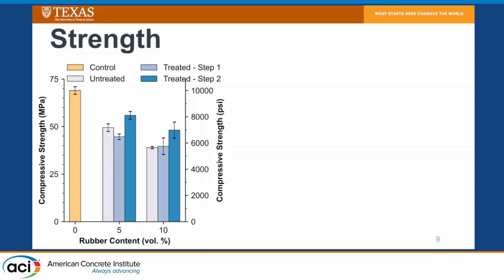As I stated before, once we start introducing rubber into our composites, we get this reduction in strength, so that wasn't surprising. We do see that when we compare the untreated bars to the light blue bars after that step 1 treatment process, we actually get this reduction in strength. So we see that even though step 1 was able to reduce the contact angle measurements, so increase hydrophilicity, we still didn't necessarily have good bonding between the rubber and the cement, which means that we needed to do step 2, right? So when we look at step 2, which is the dark blue, we actually see that we have this increase in strength, right? So we can see that with the 2-step treatment process, when we compare the untreated and the dark blues, we do see that we get this increase in compressive strength.